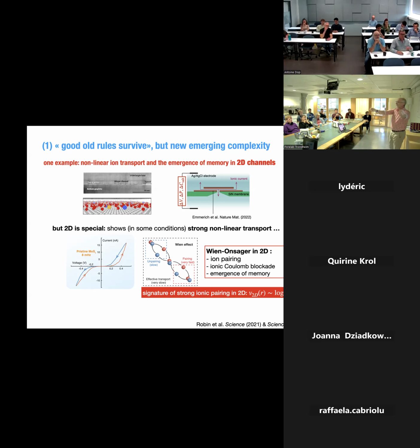So, for example, some ions which are strong in the bulk, meaning they separate, can become weak in confinement. So you make a lot of pairs. And this is boosted when the confinement is insulating, actually. And so we proposed a description where you have this ion pairing. And of course, if you have a pair, it does not conduct electricity. You put an electric field, it's neutral, so it will not move. But then, of course, the positive want to go this way, negative this way. At some point, you will break the pair. And that's the basics of the 3D Wien effect that Onsager explained.